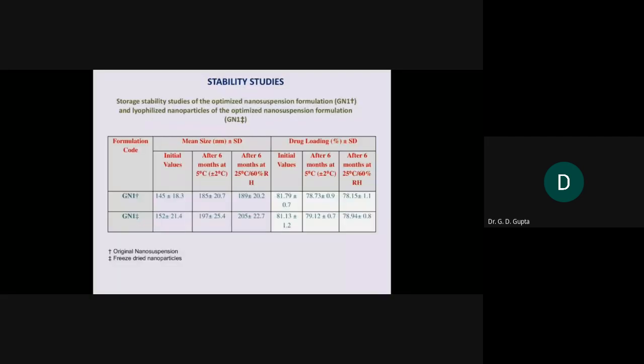Now, if we talk about the stability studies, we can find the results after storage for 6 months. We used the optimized formulation code GN1 as the initial, and GN1 double dagger as the freeze-dried nanoparticles. The initial particle sizes were 145 and 152 nanometers. After 6 months at 5 degrees centigrade, the particle size slightly increased, and after 6 months at 25 degrees centigrade, 60% relative humidity, again there was a slight, insignificant change.